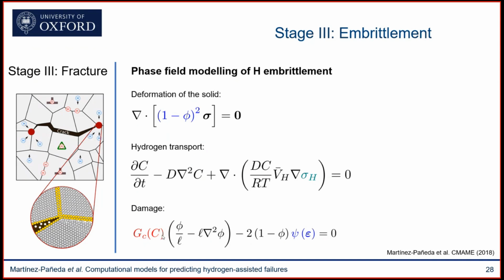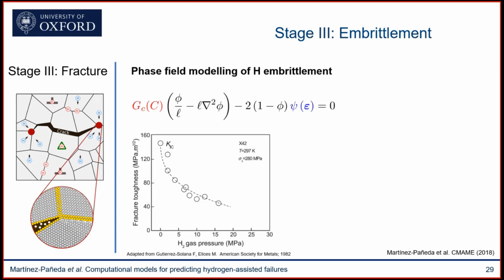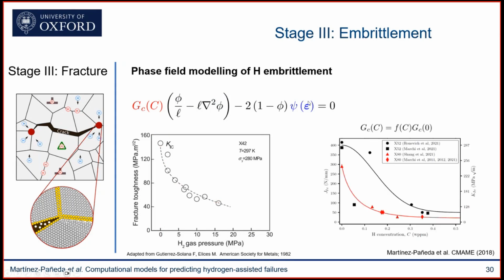And I think that the good news is that this framework is universal. So there are many ways that you can approach it. One way is, of course, a phenomenological way. And many of our industrial partners follow this approach. We have lots of experimental data of fracture toughness versus hydrogen gas pressure. So we could just feed that data and input this into the model. For example, you can see here, this is for an X42 steel, and this is for two other pipeline steels, X60 and X52. You can see there's enough data.